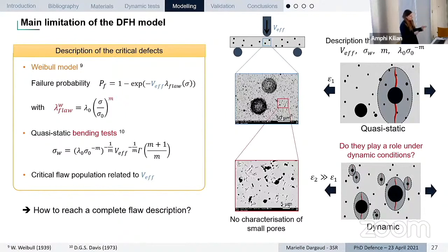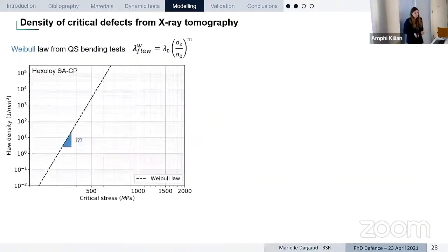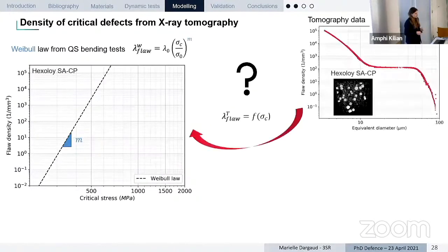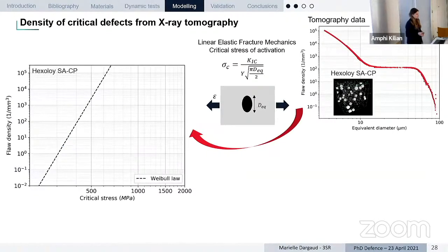In order to reach a complete description of the flaw population, what we did is that we used X-ray tomography. So here you have the classical approach with the Weibull law obtained from quasi-static bending test, and the Weibull modulus is the slope. The question is, how can we use the tomography data to have this plot of the cumulative flaw density according to the critical stress? To do this, we can use the linear elastic fracture mechanics, where we express the critical stress of activation of a defect according to its size.